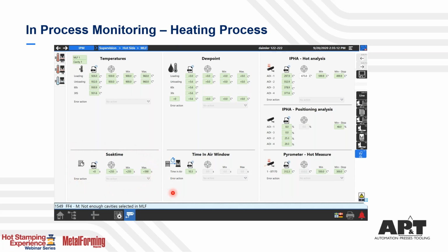So this is the monitoring part as well as the control part, because what we can do here is set limits, set boundaries for certain parameters that we would first of all like to monitor and collect data on, but then also use those boundaries to control the process. In case you go out of those boundaries, you can set certain conditions in the press hardening line for what should be done with those components that are out of bounds.